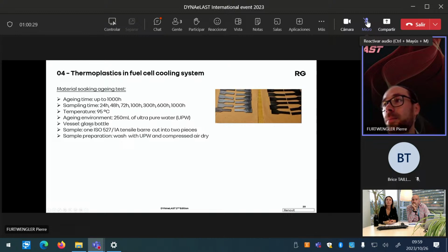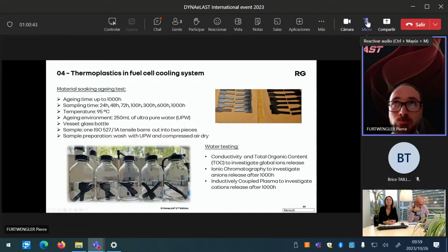a sealant which is not paper, otherwise you have contamination of the water. We set the temperature at 95 degrees, and we have aging time up to 1000 hours. Basically, it just looks like this. The purpose is to have something which is as easy as possible, to be very practical, and to have a good screening of all the TPE compounds we can have. So in this case, all of them are TPE. And what we do at the end of the aging time, we test mainly the water. So we test the total organic content to investigate the global ion release. We also perform ionic chromatography to investigate the anion release.